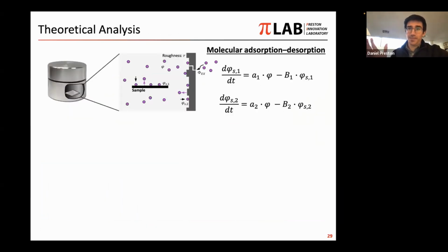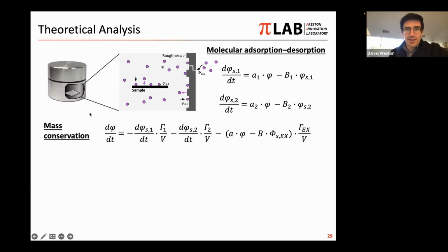We applied essentially the same adsorption-desorption competition analysis to try to understand the performance of these containers. In this case, the sample is surface 1 here. The wall of the container is surface 2 here. And we find that due to some mass conservation, we can set up an equation here that's dependent on the surface area of the inner wall of the container. And so that's where this parameter comes into the model. We also have some surface here. It's an imaginary surface that represents leaks. And in addition to this, we look at the contamination within just the environment itself.